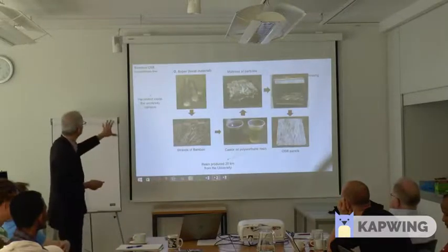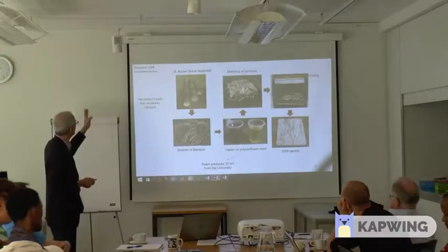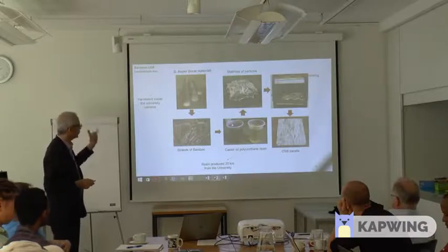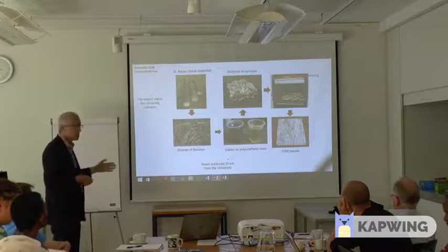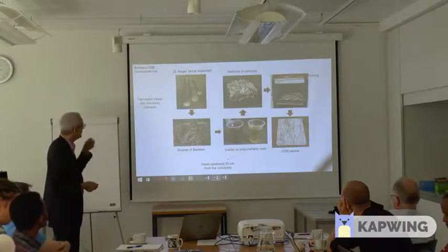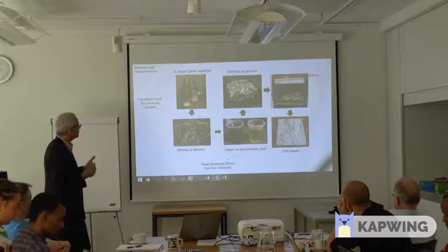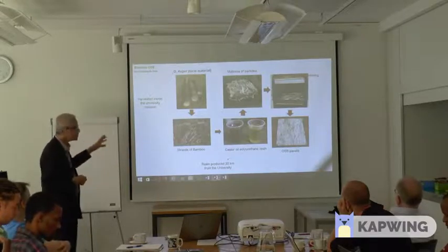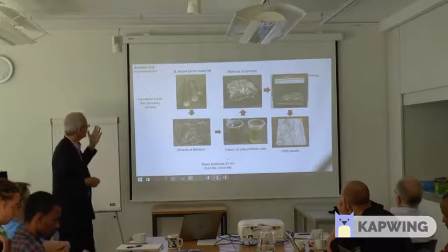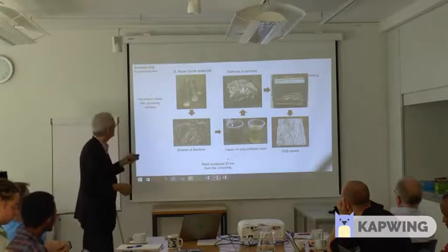So in this study we are using a formaldehyde-free glue. That's a polyurethane resin based on castor oil that's available in the Brazilian market. So we tried to see how it works in OSB panels produced with strands of bamboo. That's another doctorate study using this thermal pressing.